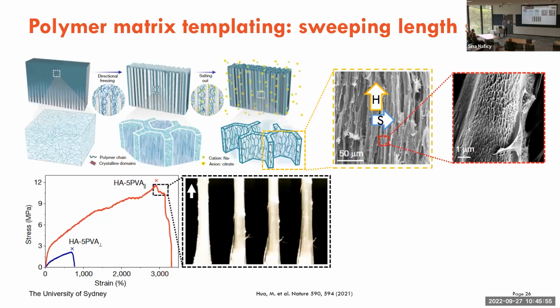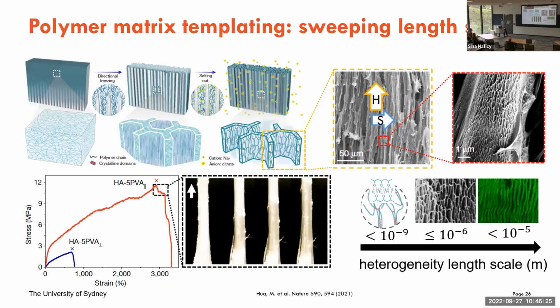the mechanical properties. These are actually extremely tough materials. So for those in the field of mechanical engineering, they would see that this is quite a lot of stretch. This means that you have stretched the material 3,000% in one direction without failing, and the other direction is 900%. And the stress that they can go under is basically much more than what a leaflet can have. So techniques like this could actually bridge the whole length scale in terms of heterogeneity.